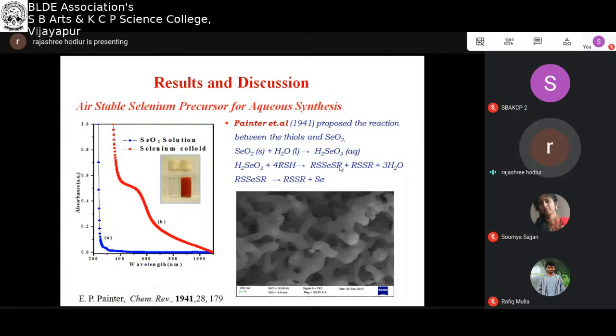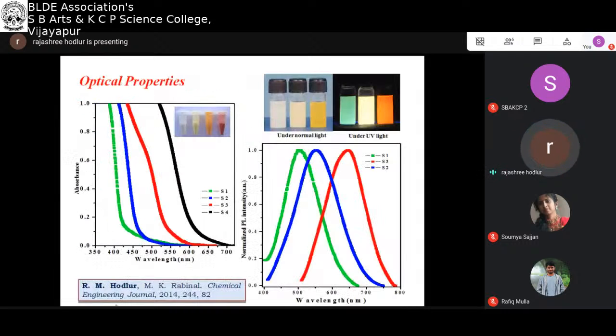So here, in order to understand the chemical reaction process, since I told you we used 3-mercaptopropionic acid, what was reported here is that this 3-mercaptopropionic acid, which was used for controlling the size and shape of the particles, not only acts as a capping molecule, but also acts as a reducing agent. So that was confirmed, and this work is published in Chemical Engineering Journal, where we attempted to show that capping molecules like thiols not only act as stabilizing agent, but also may act as reducing agents.